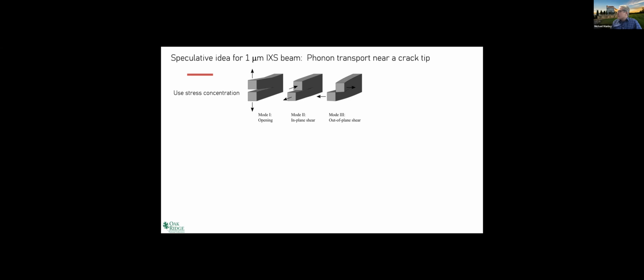So I thought about, what would it look like to measure phonons near a crack tip, where you use the stress concentration near the crack tip to modify the strain states? It's an interesting problem to look at, because for one thing, it doesn't take much to create very large strains because you're using this concentration. It's also pretty well understood because it's a very important problem in mechanical properties. And if a material's self-irradiating, the temperature can affect the tendency to crack, or how a crack grows. So knowing how the thermal conductivity varies around a crack tip could be interesting.